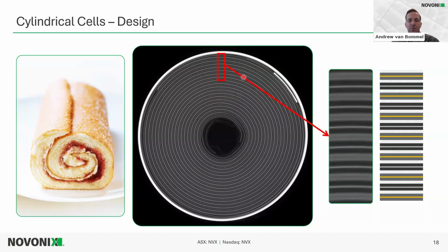So I'm showing an outsourced CT scan of one of our 18650 cells. You can see if you zoom into this section here that you can see the stack. So the very dark areas are the NMC, where I'm indicating here, the aluminum and NMC, and then the lighter areas are the graphite, copper, and graphite. So you can see that this stack, if we do a cutaway of this, corresponds to the same stack that I showed of all the different layers for the multi-layer pouch cell. So we have all those layers in contact. In this case, it's all from one single, long piece of anode electrode and a long piece of cathode electrode, as opposed to the stack cell that had 7 anodes and 6 cathodes. I'll show that next.